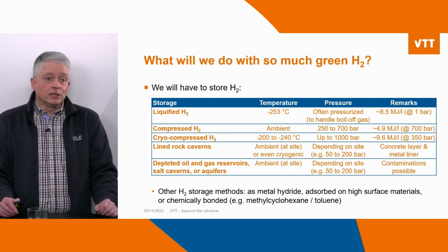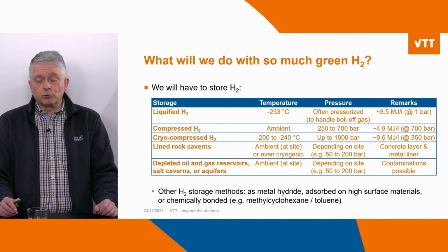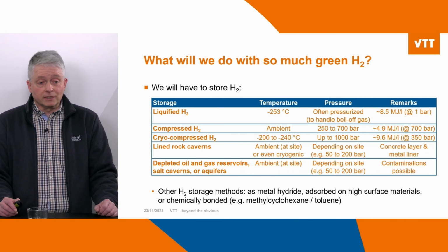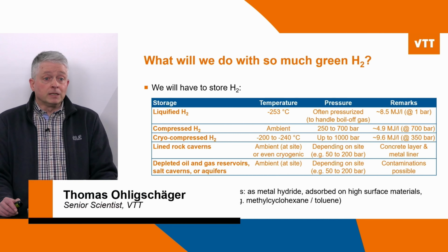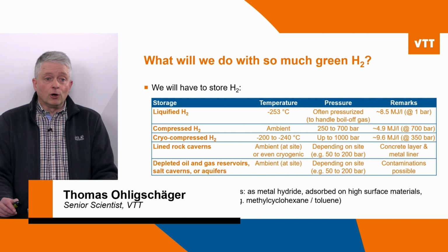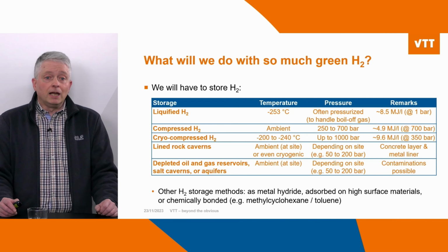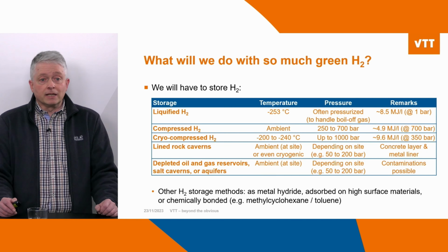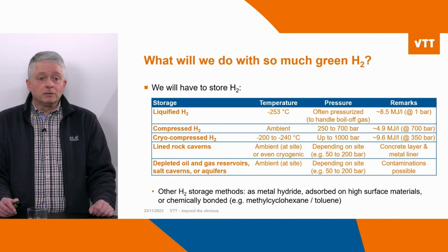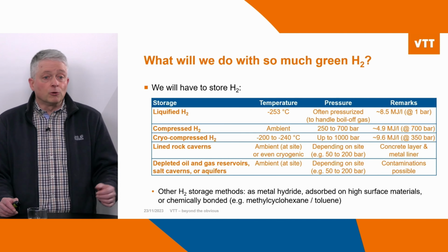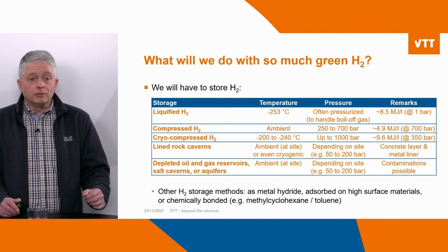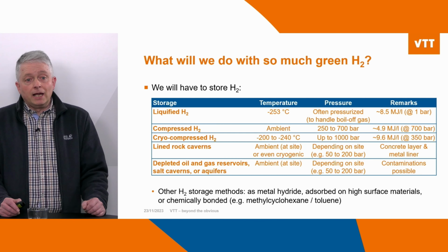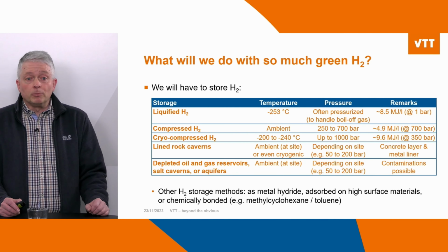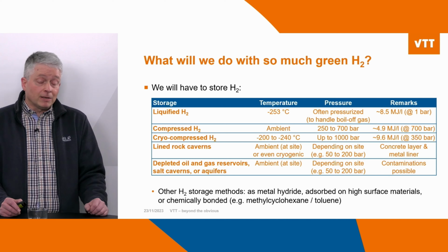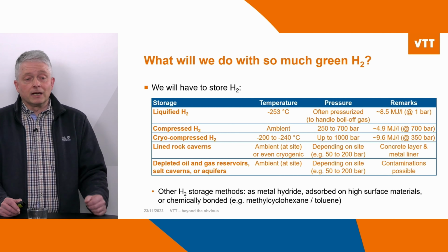For long-term storage, we can use lined rock caverns, which is possible here or will probably be more used in Scandinavia. In Central Europe, where we have depleted oil and gas fields, it's possible to store the hydrogen as natural gas is stored at the moment. The conditions here are also pressurized and at temperatures that are there at the site. It's also possible to store hydrogen as metal hydrides, which is used only in special applications, for instance on submarines. And it's also possible to absorb hydrogen on high surface materials, or it can even be chemically bonded to chemicals so that the hydrogen is not stored as gas anymore.